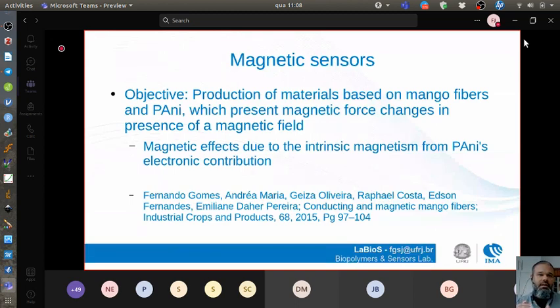Now, thinking a little bit more about this kind of magnetic sensors, we proposed to use mango fibers modified with PANI. Only PANI. Okay. So we produced mango fibers, which were modified with PANI. And these fibers, after the modification, presented magnetic force.